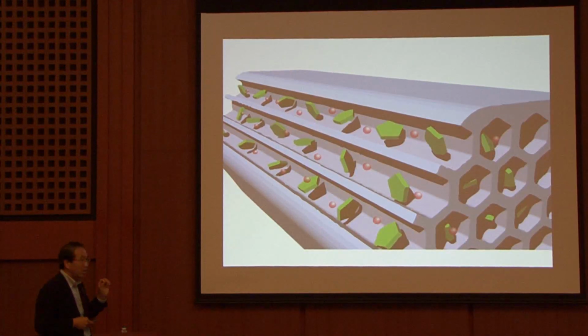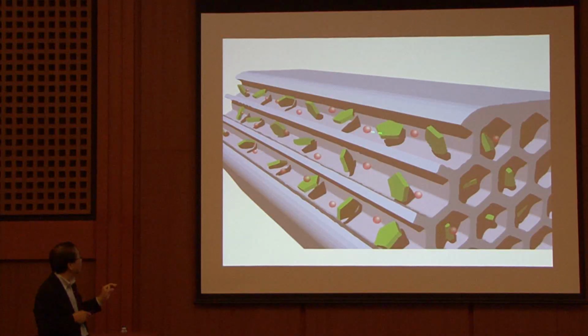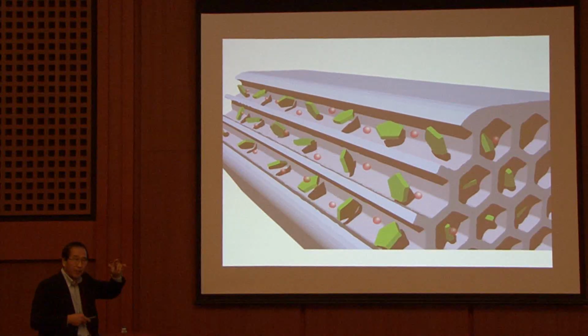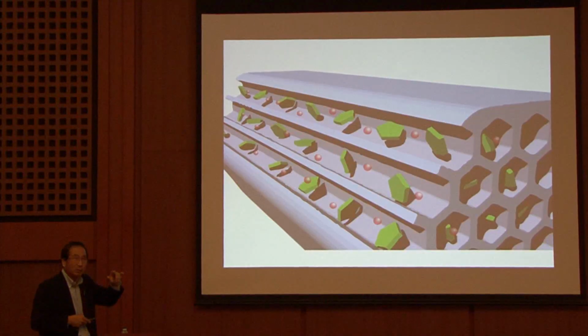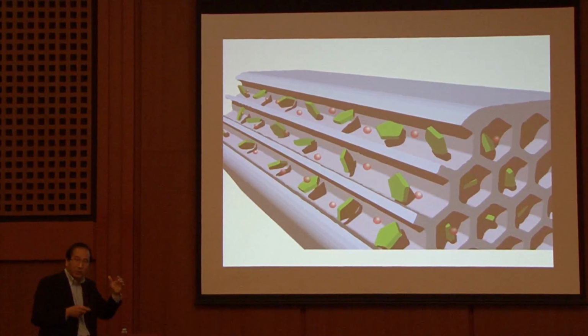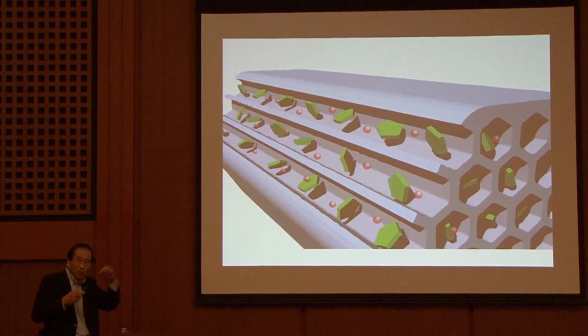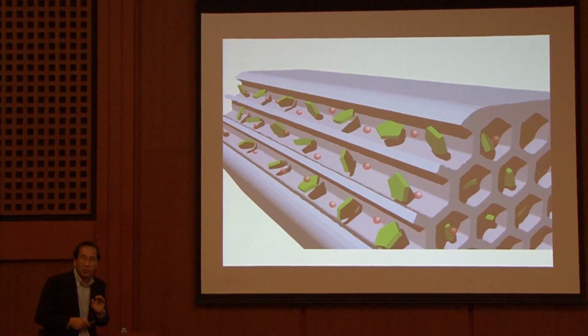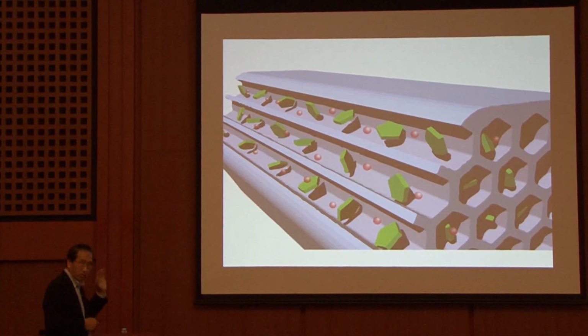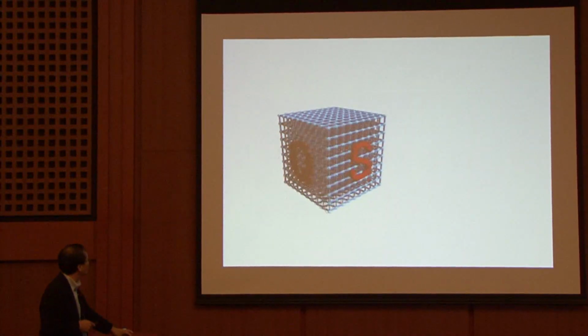We observed the NMR spectrum and so on, and we characterized what happens in the case of imidazole. The imidazole in the channels is not strongly trapped, it has a sort of freedom of motion in the channel. That is the key. But if the channels are very large and many imidazoles are accommodated, it does not work. So it's a very subtle issue for higher conductivity. But anyway, we succeeded in obtaining this kind of result.